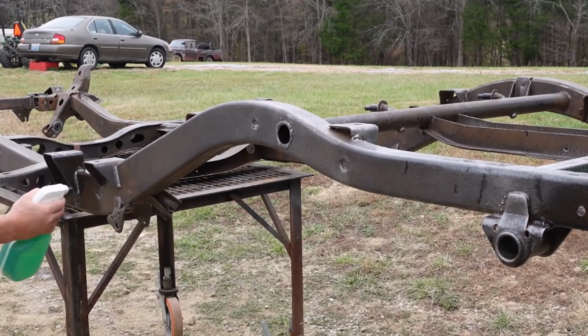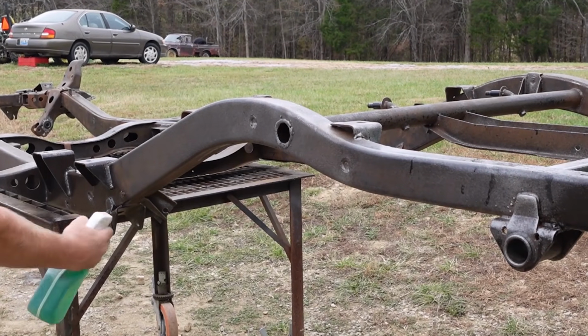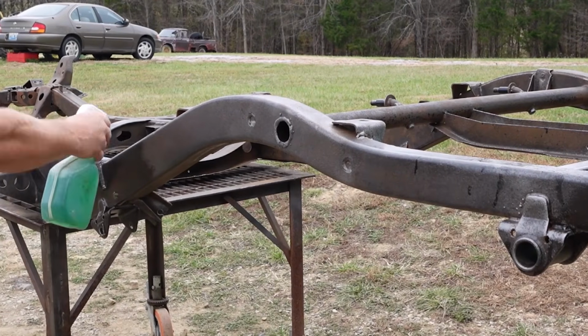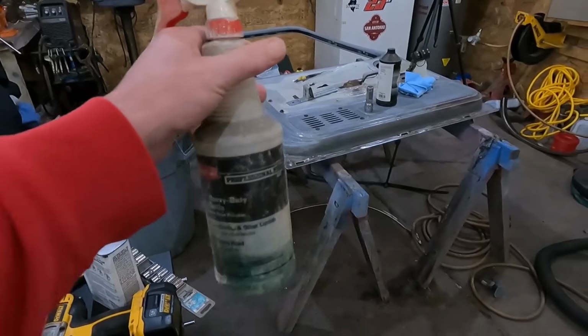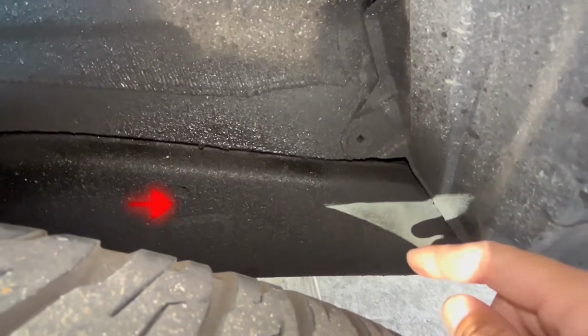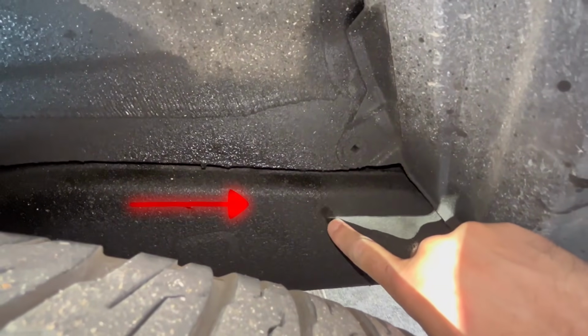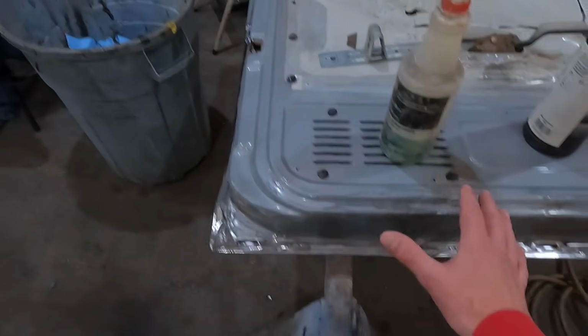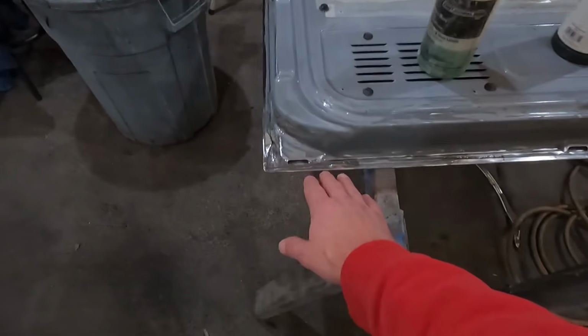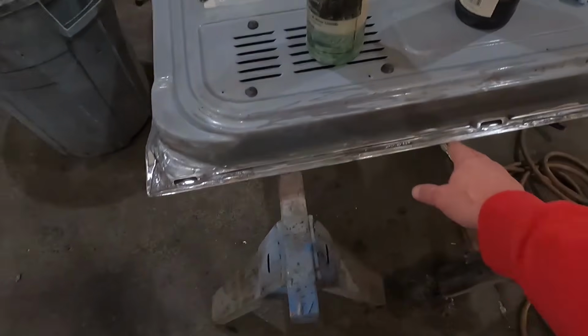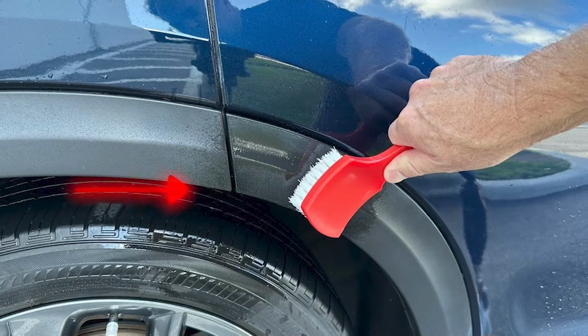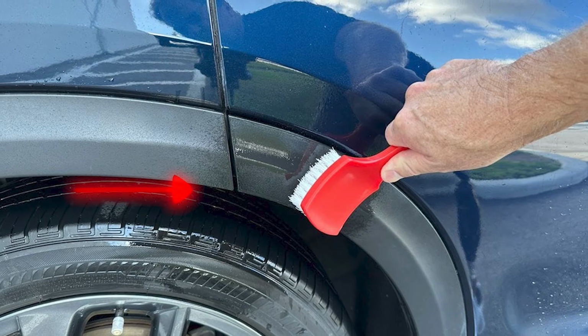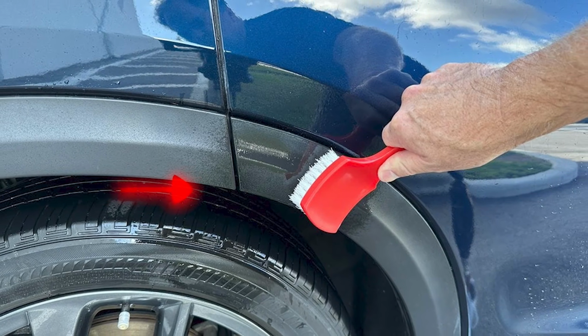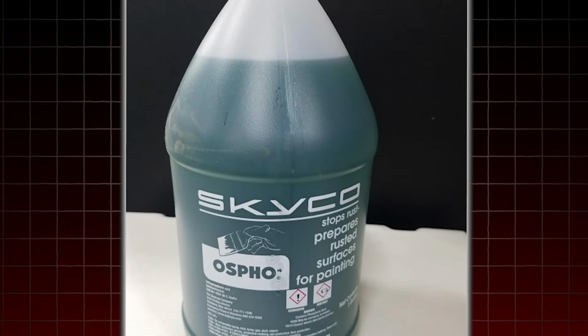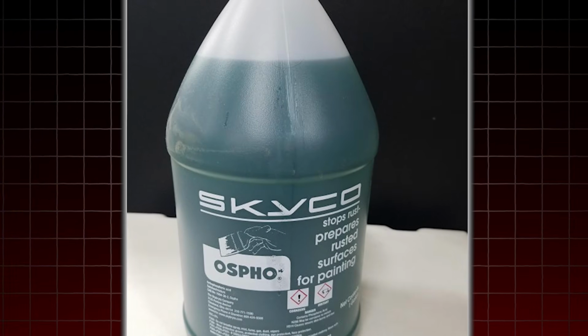In our testing on moderate frame rust with early pitting, Ospho produced measurable conversion into pit surfaces where the lighter gel products had failed to reach. Multiple applications with brushing into pit surfaces allowed the more fluid Ospho formula to penetrate into surface irregularities more effectively than thicker gel products. At the 60-day assessment point, Ospho treated surfaces showed less subsurface rust progression than surfaces treated with the Rust-Oleum gel. The risk that the product reviews rarely mention is the residue requirement.